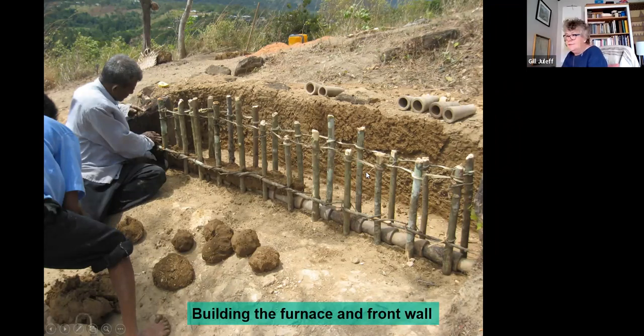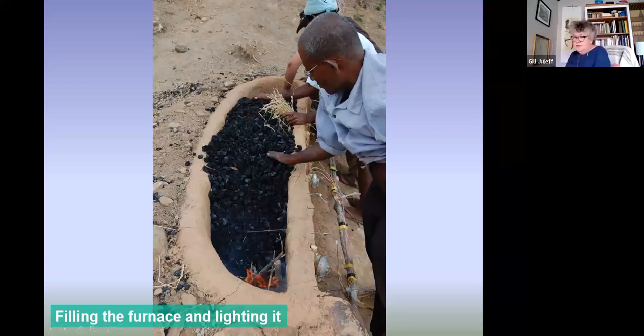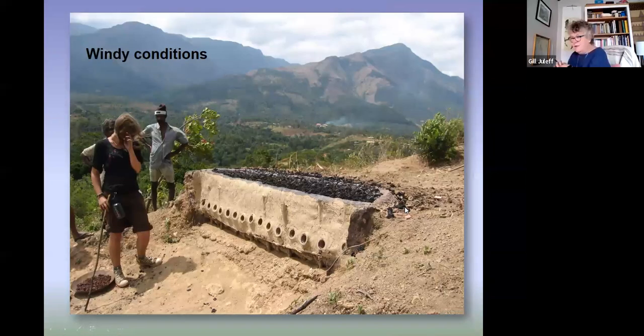So this is the furnace after it's been built, filling it with charcoal and getting it lit and running. And this is what it looks like reconstructed, and we're starting to heat it up. You can get an idea of the wind by looking at people's hair and shirts and the trees and the smoke in the background. The wind here is not only high velocity, it will blow during the monsoon anything from 35 to 75 kilometers an hour. But what's also very important, it's almost monodirectional. So it's coming directly from the west. So locating and orientating your furnace is a very important part of the design of this structure.